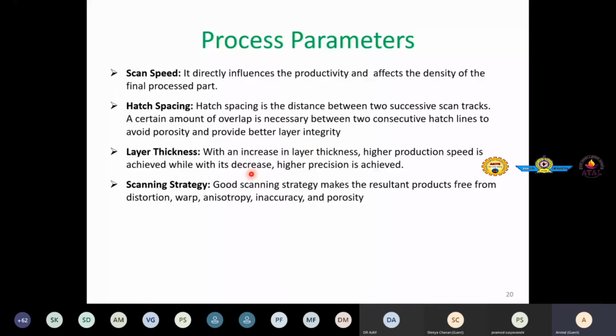A scanning strategy, a good scanning strategy makes the resultant product free from distortion, warpage, anisotropy, inaccuracy, porosity, and thermal stresses. We are going to see some of the aspects in the subsequent slide. So, since we are talking about layer-wise production, then repeated thermal cycling effect, so you can expect that there will be a lot of thermal stresses developing, and that should be kept at an acceptable limit to avoid distortion and warpage.